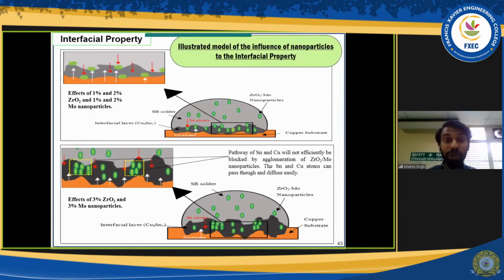So again, what happens? I have made a model, because we can't really see the IMC image clearly, as sometimes the IMC image is too technical. So I've come up with a model so that we can clearly see what is happening. For the 1% and 2% zirconia and the 1% and 2% molybdenum, after detection of the nanoparticles from the SEM and XRD, I've seen that they are mostly distributed at the interface. So they actually block the diffusion process. You can see I've highlighted in black border and I've shown what happens. The red arrow here is the Sn atoms and the white arrows are the copper atoms. So they are being blocked by these nanoparticles.